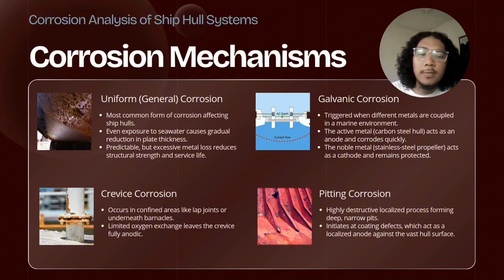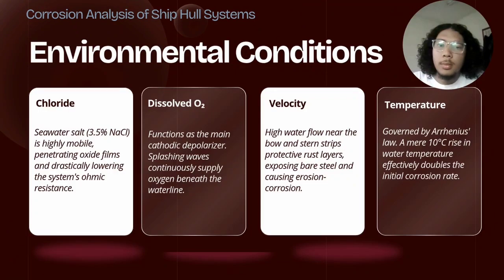Similarly, pitting corrosion forms deep, narrow, and destructive holes. It typically initiates at a tiny defect in the epoxy coating. Because the exposed steel area is so small compared to the rest of the protected hull, it takes the brunt of the anodic attack. None of these corrosion mechanisms happen in a vacuum.